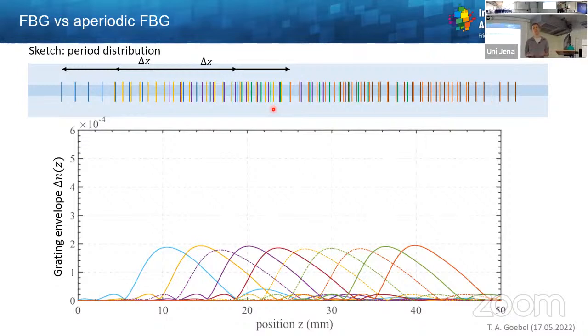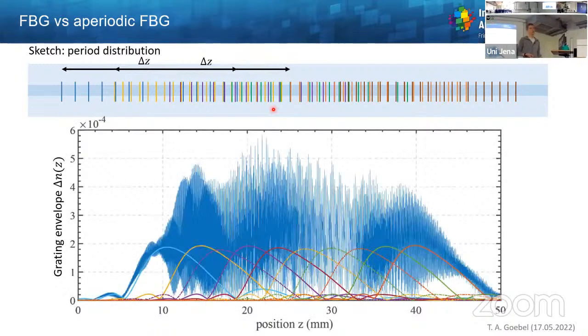And not only the period is now changing, also the envelope of our refractive index structure. This is a kind of interference effect that we see here. So this is really the refractive index envelope. The period we inscribe is around 500 nanometer, and what we are seeing here is 50 millimeter. So this is the envelope we need to realize inside of our fiber core. You see this is getting very complex, and it's a very challenging task to inscribe such fiber Bragg gratings with a very flexible period adaptation and at the same time a very flexible envelope change.